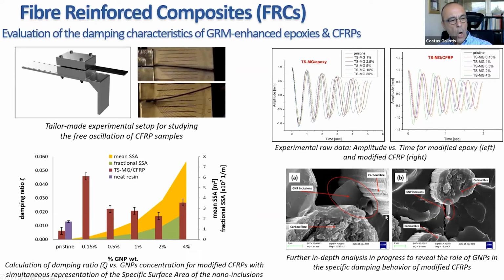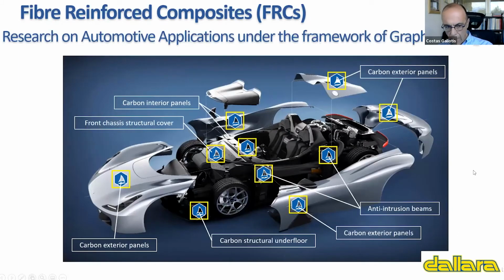So again, low percentages are much better. And this is exactly what we are discovering. For fiber reinforced composites, in the Graphene Flagship, in which I lead the composites work, we look at, I don't want to say too much because these are still not published work, different parts of a car. In some cases, we improve the fracture toughness. In other cases, the damping characteristics.